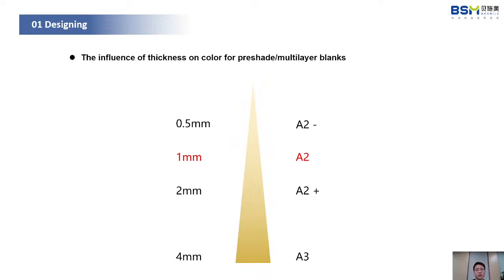Of course, the thickness will also influence the shade for the pre-shade and for multi-layer blocks. As I said, when the thickness is 1 millimeter, for example, if it's an A2 disc, we can get A2 as a shade result. But if the thickness is only 0.5 millimeter, we will get a lighter shade. And when the thickness is bigger, we will get a darker shade than A2. So if we want to get a more accurate shade, we recommend to use 1 millimeter for the crown designing.